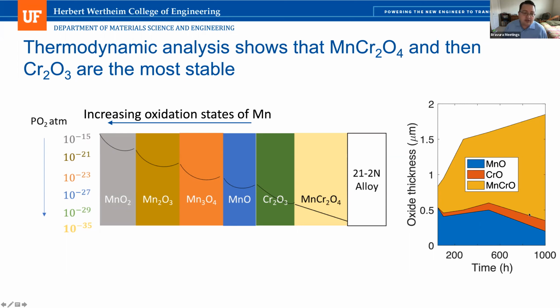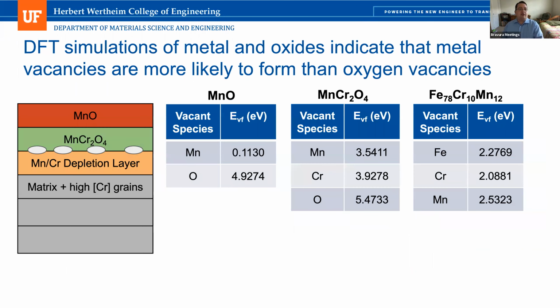But a valid question then is, well, if the manganese oxide is less stable, why did it form in the first place? One possible reason for that could be kinetics. So it could be that the manganese is able to migrate more easily and start to form this oxide layer. So we started to look at this more now with density functional theory.